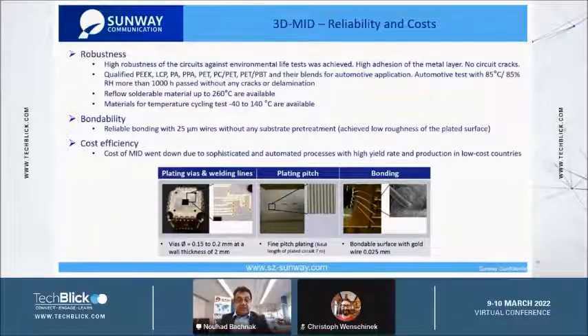Here I show some applications. The first one, for example, is a part where we have holes inside, and this is made of LCP material. And you know, LCP, if you have holes, you will have a weld line, and if you plate over a weld line, you may have cracks. With this process, we can plate over a weld line without having any cracks. The second one is a part where we have more than 7 meter long lines or structure with a very fine pitch. It's three-dimensional. The material is PA. It absorbs a lot of humidity without any cracks. And the third one is to show the bonding capabilities.